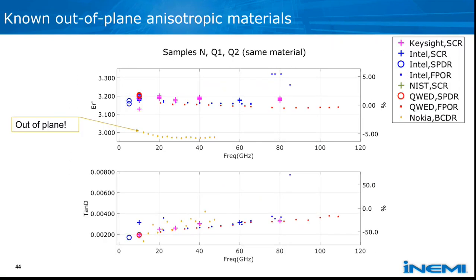So here are some materials we expected to be anisotropic out of plane. The previous ones I showed were not expected to show that, but happened to. With these, we can capture and show that there is a slight out-of-plane anisotropy—the out-of-plane permittivity is, again, lower than the in-plane.